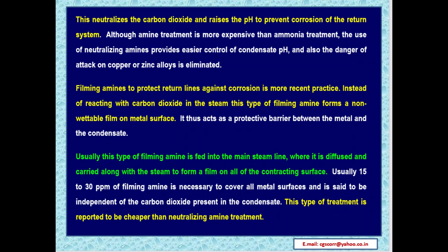Usually, 15 to 30 ppm of filming amine is necessary to cover all metal surfaces and is said to be independent of carbon dioxide present in the condensate. This type of treatment is reported to be cheaper than neutralizing amine treatment.